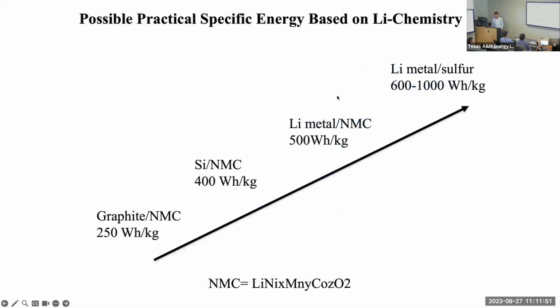But if you could do that, this is the pathway. Graphite with NMC combination is 250, now maybe close to 300 watt-hours per kilo. Silicon anode coming in with NMC gets to 400, might be even 500. Metallic lithium with NMC, that's 500. This is the famous Battery500 consortium. We try to get to 500 watt-hours per kilogram, and I serve as co-director of the consortium. Lithium metal and sulfur can potentially get to 600 or 1,000 watt-hours per kilogram.